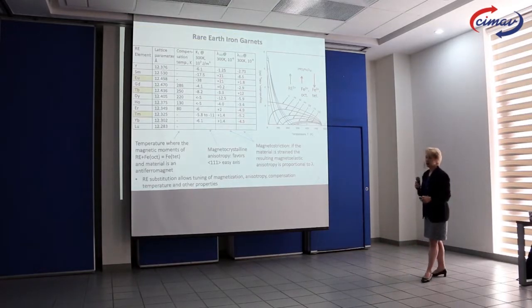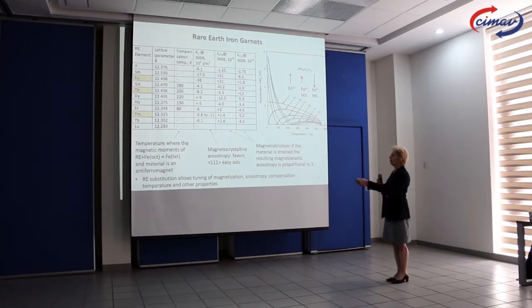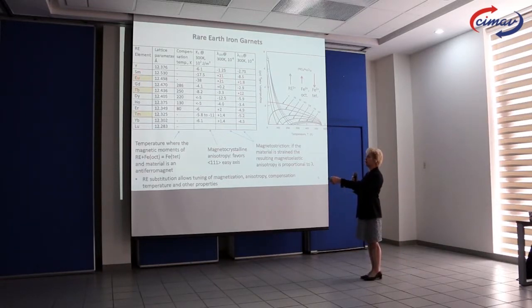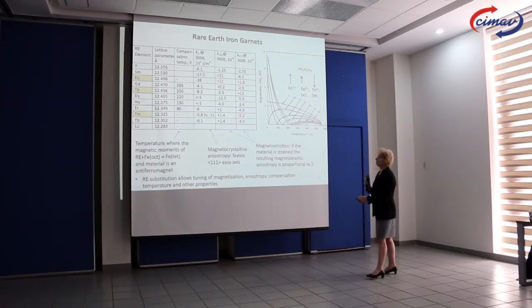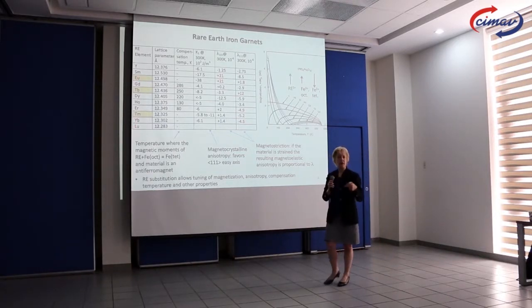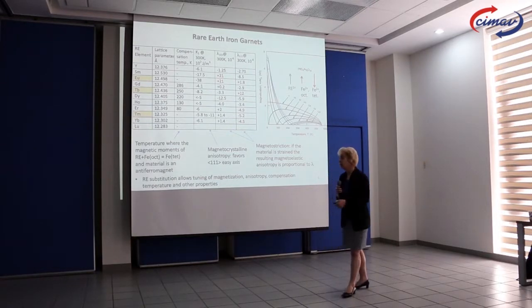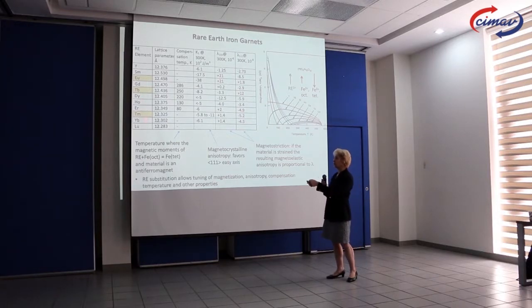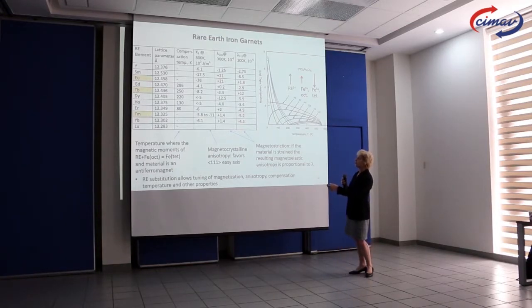Okay, so when we're engineering these garnets, I've got here some data that shows you what happens as we go down the series. So this is the series of rare earths, the lanthanides, compared to yttrium in the iron garnet. And we can see the lattice parameter gradually goes down as we go along the row, because these ions are getting smaller. There's more positive charge at the nucleus, it pulls the electrons in more, so the ionic radius of these ions gets smaller as you go down along the row, and therefore the lattice parameter gets smaller as well. We have changes in the magnetic anisotropy. This is the magnetocrystalline anisotropy, which is always negative, but it varies somewhat in size. However, this is actually quite small.